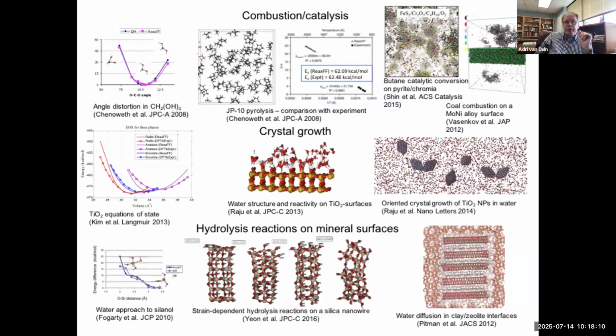Very quickly going over some examples before I go to the more graphic thing, just to show you the diversity of research that has been done with ReaxFF. So a big increase in popularity was in 2008 when we developed the first combustion ReaxFF description, where we actually could simulate pyrolysis and oxidation. And then we managed to transfer that into catalysis. So we could look at, for example, how hydrocarbons interact with chromia and other types of catalysts.